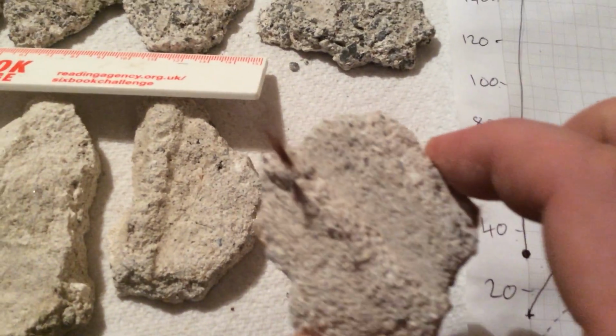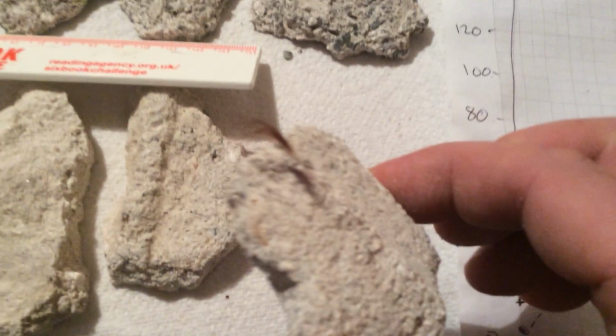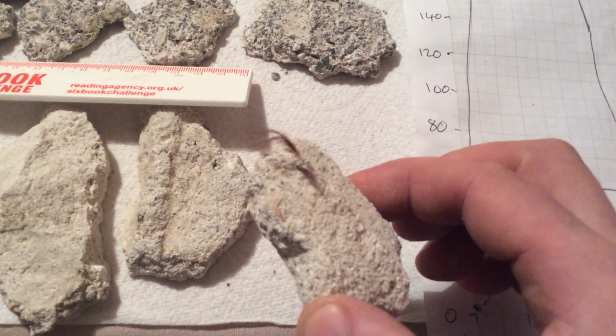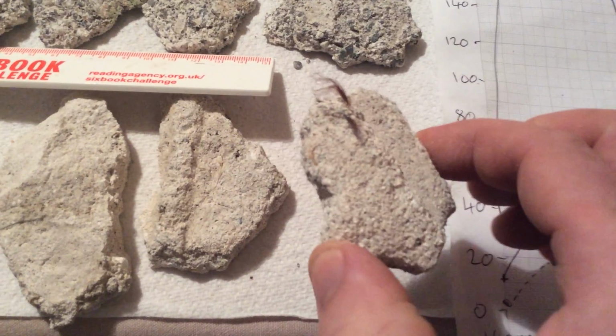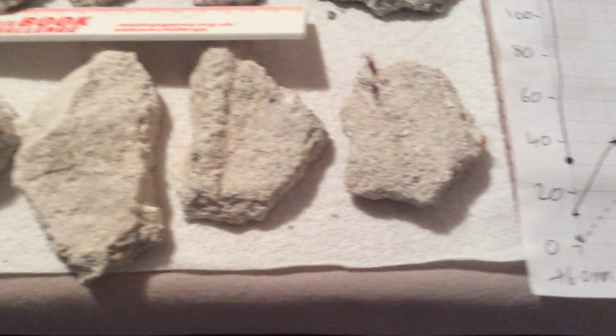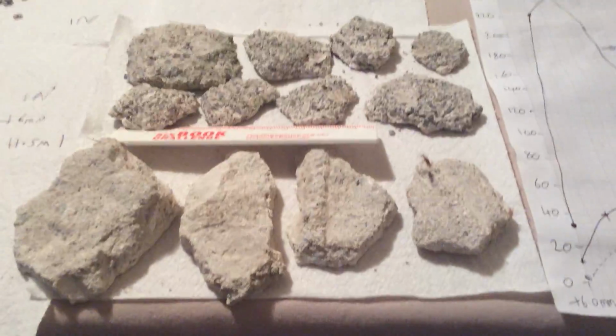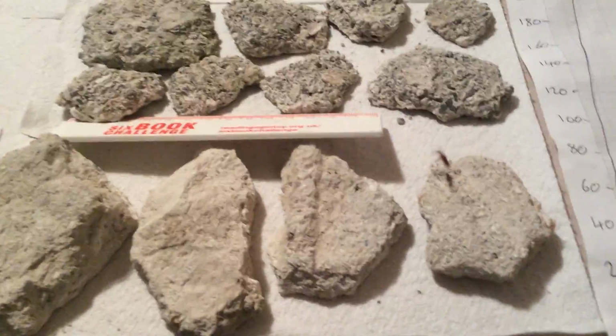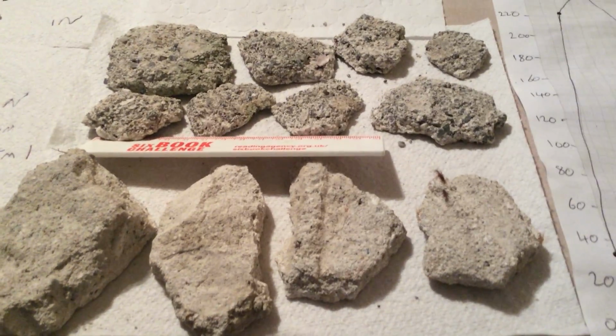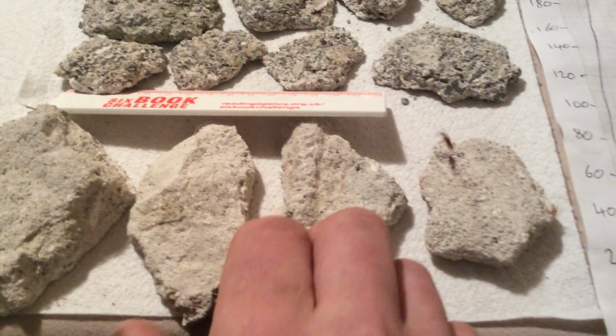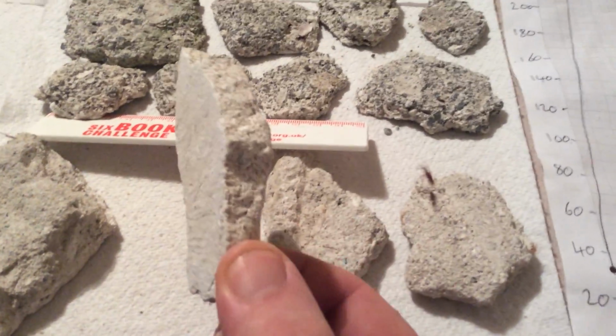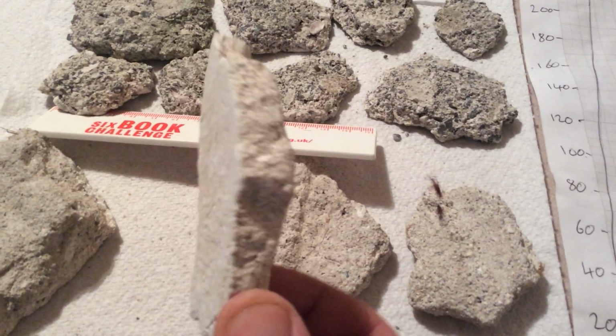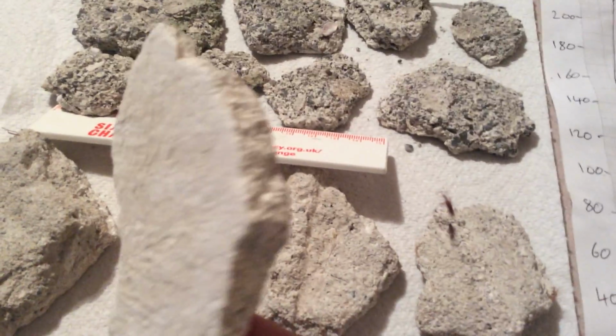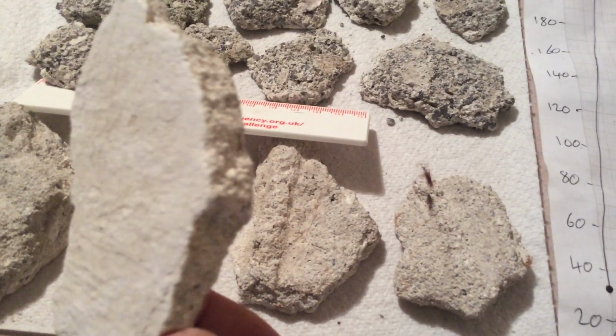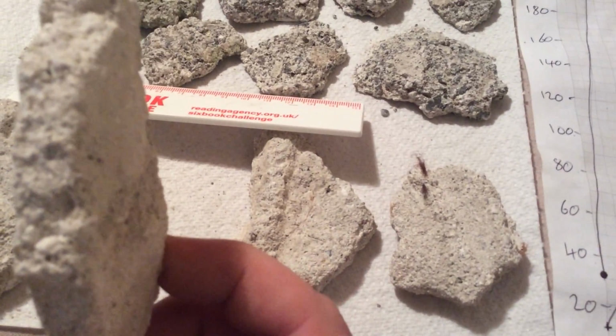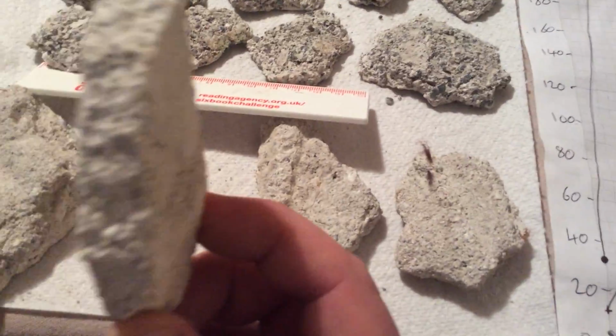See a little bit of, looks like to be horse hair, but the fibres in there are very rare indeed. If you compare them to the modern hydraulic plasters, you would have a fibre every millimetre or so. So the material doesn't need fibres in it to remain robust, and it doesn't need any crack suppression from the presence of fibres.